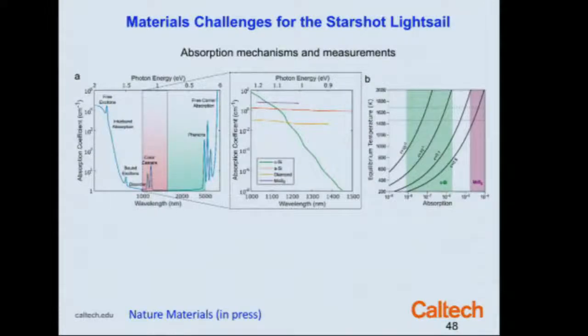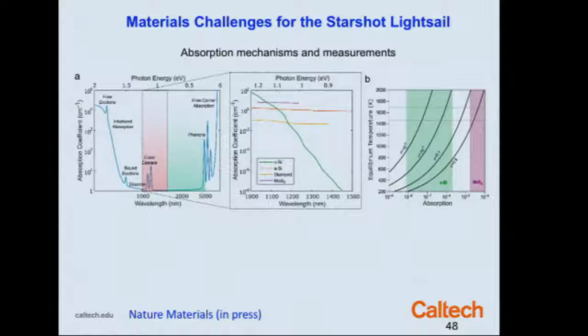So what we need is to have materials that have very, very low absorption coefficients. So this is the absorption coefficient in inverse centimeters of materials that we found data for: molybdenum disulfide, amorphous silicon, crystalline silicon, or diamond, and here crystalline silicon. And then it's important, we need to have very low absorption at the pump laser wavelength right about here. But we also can't have a lossless material here because we have to have some emissivity. I talked about the balance between absorption and emission yesterday. We have to have a material that has finite emittance. So we need some absorption here at long wavelengths outside the pump laser wavelength band such that we can use black body radiation to cool the sail. That turns out to be very important.